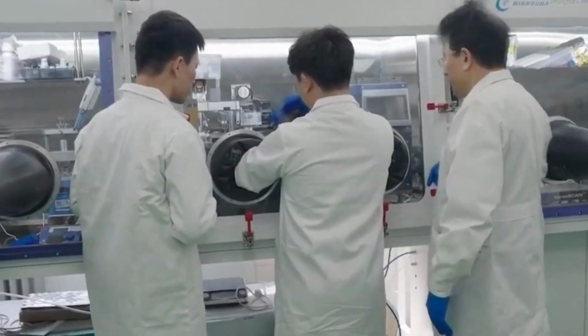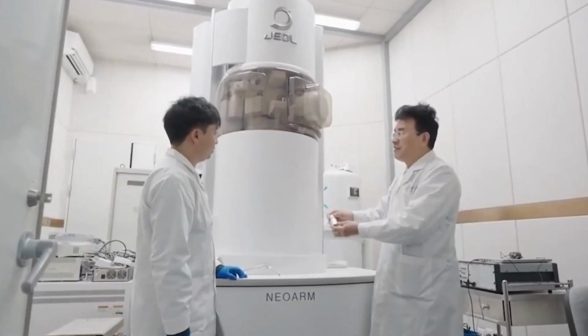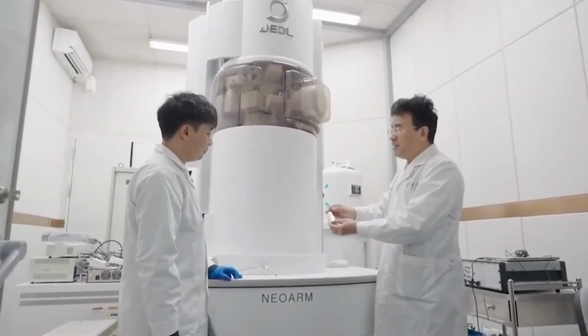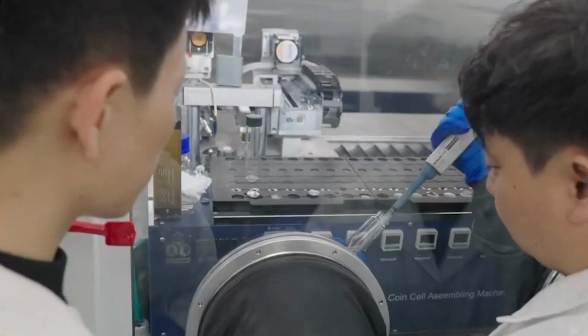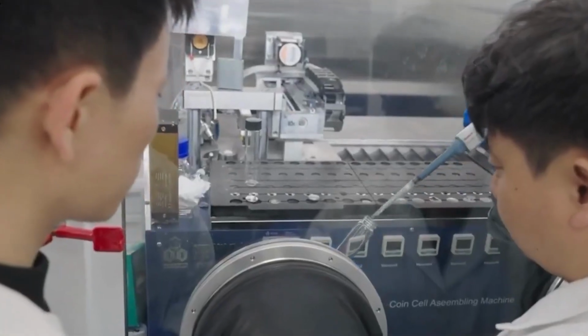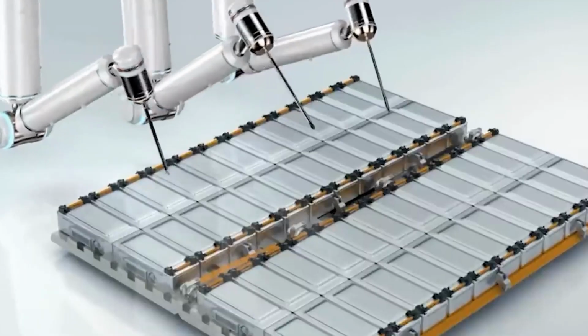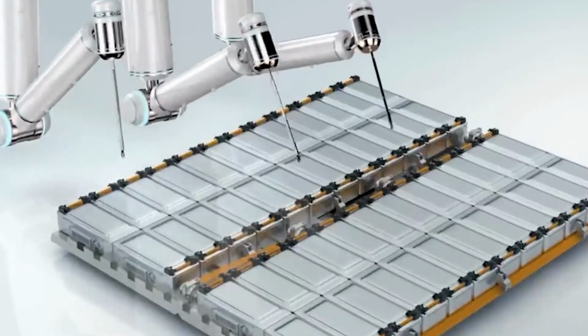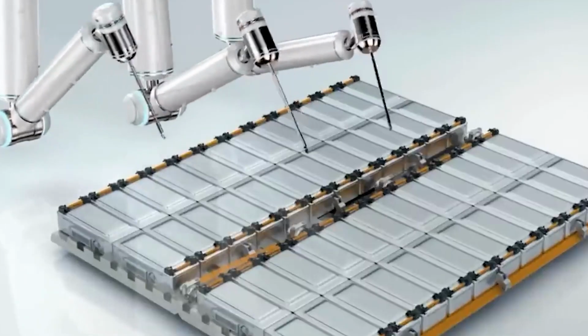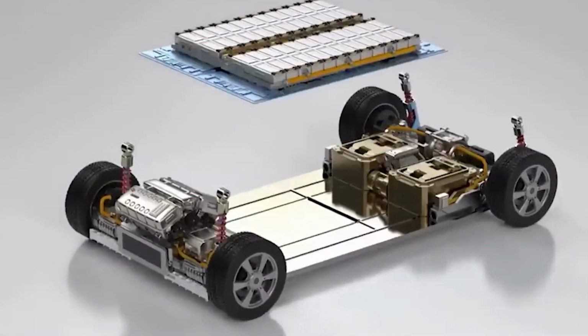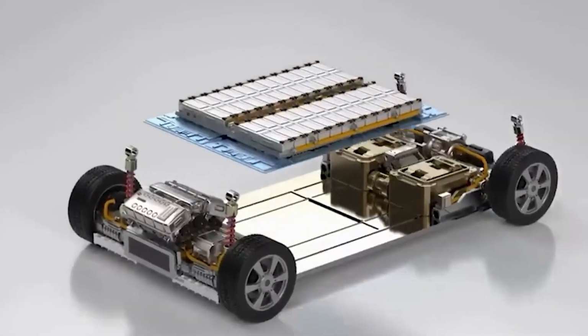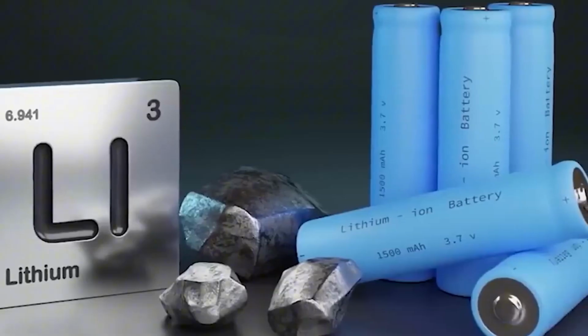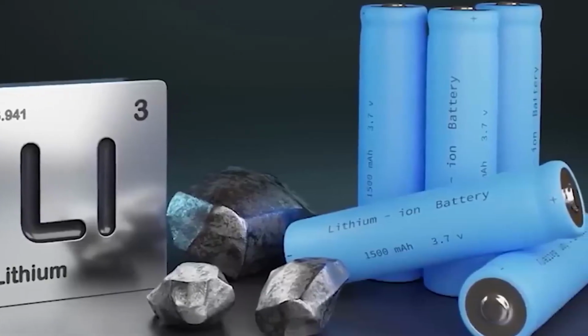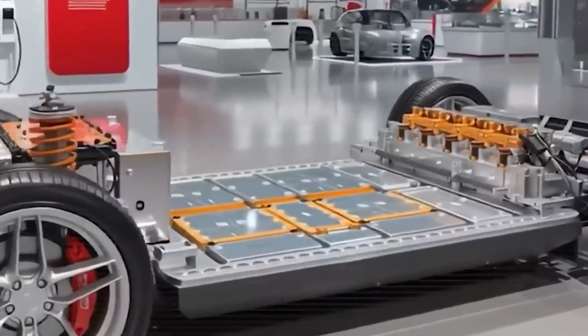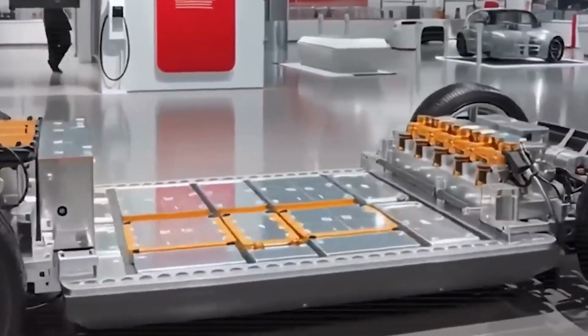Here is the detail that puts everything into perspective. Researchers expected that pushing lithium ions through the crystal faster would distort the internal lattice more severely, the same way forcing more cars into a garage faster should produce more chaos, not less. Using in situ electron microscopy, the team watched lithium ions arrange themselves in tight, orderly rows during slow charging. And that orderliness was the problem. Precise alignment locks the lattice into a rigid, strained configuration, and strain is what throttles ion movement.